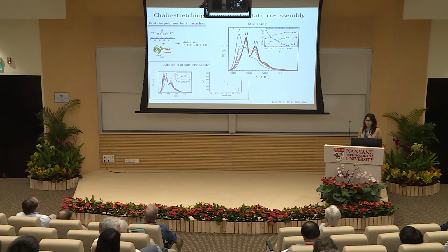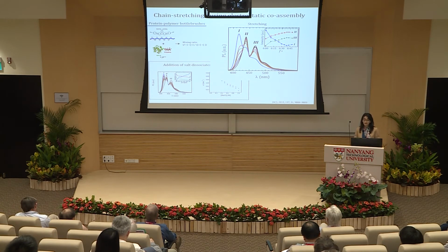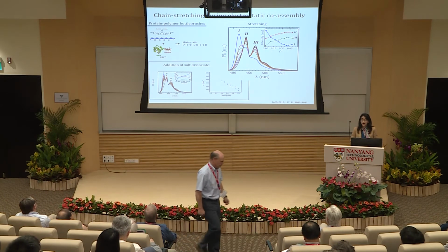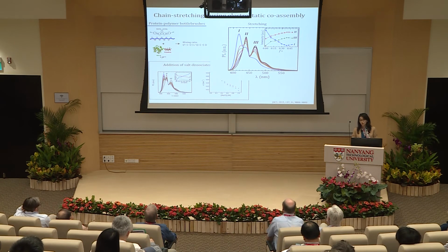But in this system, what we see is that gradual binding on the backbone is actually causing a gradual transition from the regular phase to the beta phase. As you see here, this is not a fluorescence emission shift, but literally a completely new electronic configuration. Gradually, the first band disappears, and the second and third become the prominent emission bands. And this comes to a saturation when the charge stoichiometry is reached.